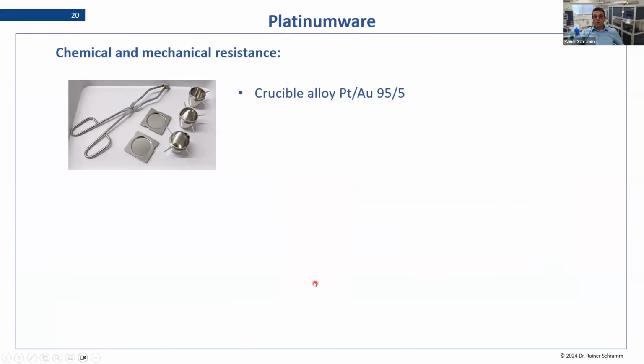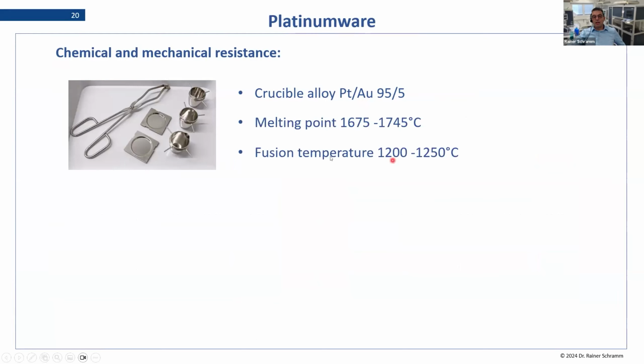Okay, platinum ware also plays a role. Normally we use platinum gold, 95% platinum, 5% gold. And the gold is used because it's also like a non-wetting agent. It avoids that your melt is sticking to the surface of the crucible, and the same for the mold. So it helps to release your bead from the mold. Typical melting point of platinum gold alloy is something around 1700 degrees. And then, of course, this is good for our fusion temperature range, which could be up to 1250 degrees.